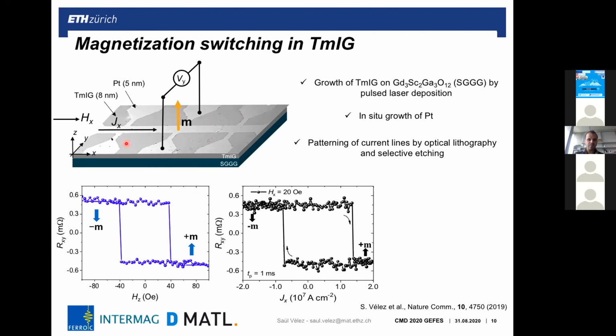So now if you apply a magnetic field in the plane and you run a large driving current, so if you send pulses, you exert torques on the magnetization of the magnetic insulator, thulium iron garnet, and you can eventually switch the magnetization.